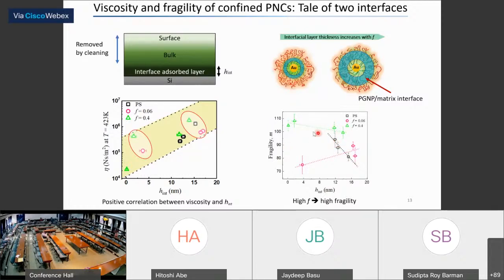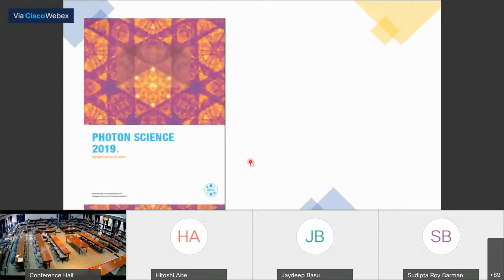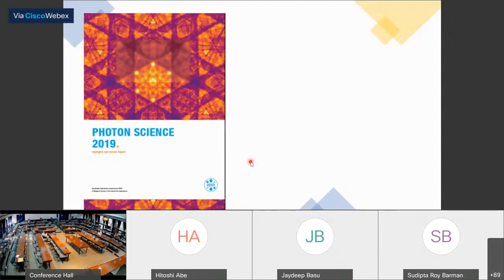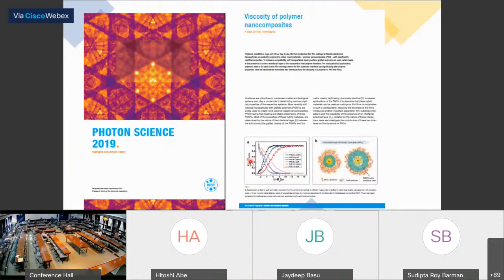So there is viscosity, there is fragility. And here you see that generally, as the interfacial thickness becomes higher, your fragility goes down. This effect is stronger in the polymer, but it is a little bit more subdued in the other, but nevertheless you can see it. So basically, we have looked at two parameters: the interfacial layer around the particle, and the interfacial adsorbed layer at the interface between the polymer and the substrate. You have these two as control knobs for varying the viscosity and the fragility of these films, and that is very critical in understanding what happens to these sorts of coatings when you think of application. So this is the work which was cited in the DESY photon science report.